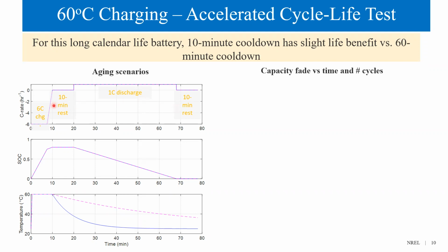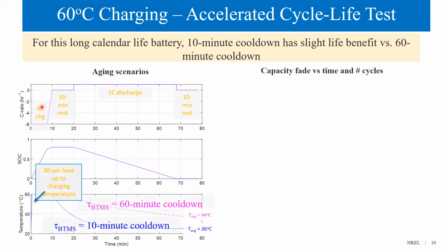We picked an aging profile like this. First, heating up the cell to 60 degrees Celsius within 30 seconds. Then after the 6C charging, there is a 10 minute rest, then a 1C discharge. And then we cool down the cell with different cooling time constants. We picked 10 minutes and 60 minutes respectively. The cooling time constant is the time to draw down cell temperature by 63%.